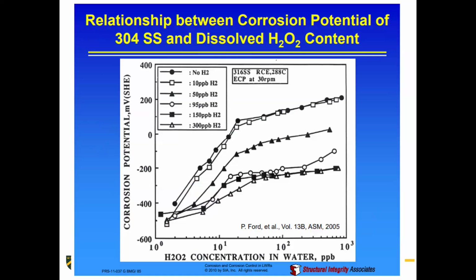So let's look at how this ends up playing out. This is the concentration of hydrogen peroxide in water versus the corrosion potential. You can see that for our no H2 present scenario, it goes up really steeply. At this point, we're well into the region where we could have intergranular stress corrosion cracking. Actually, I don't know specifically at what potential that begins. I'm not going to test you on that. I don't know it off the top of my head. But anywhere down here, like sub 200, we're usually good. So you can see by applying that hydrogen concentration, you end up dropping that pretty dramatically, even with relatively high concentrations of peroxide in the water.